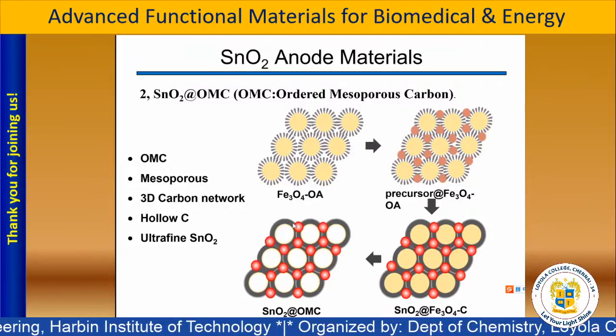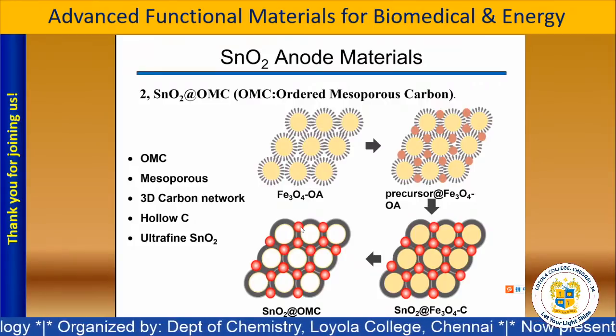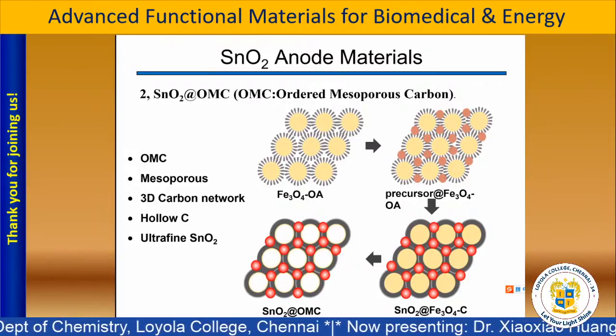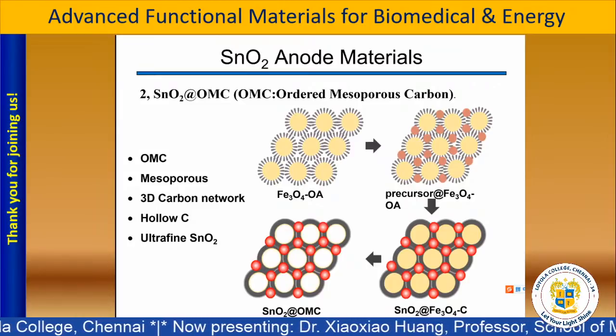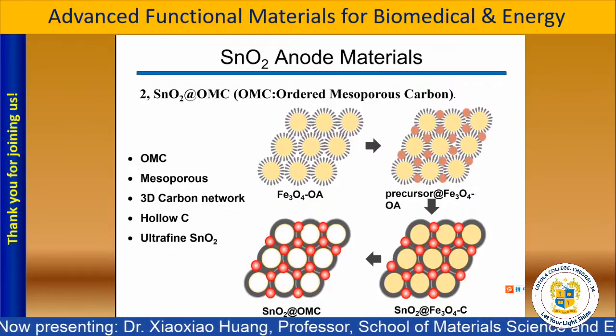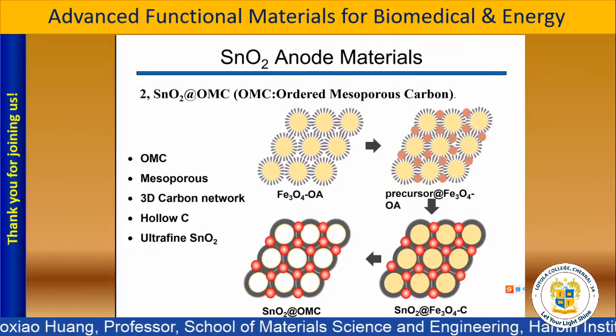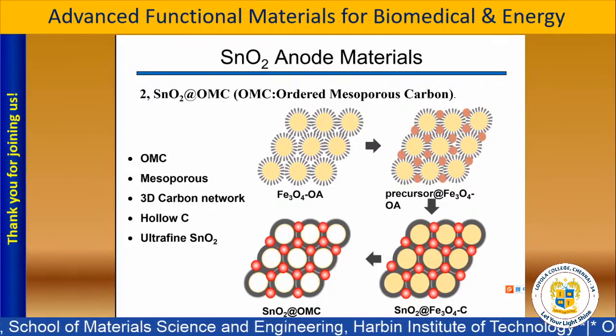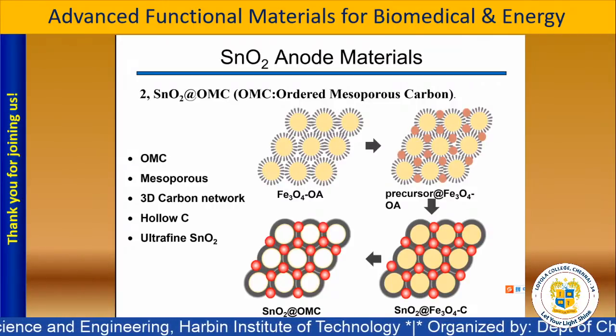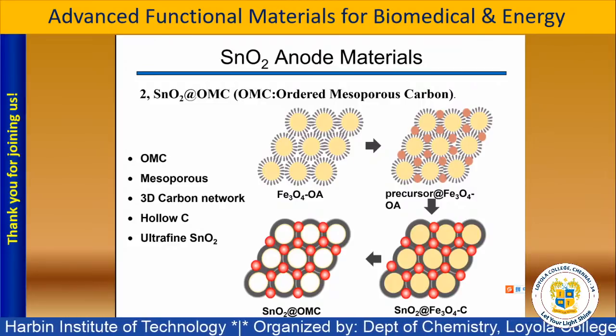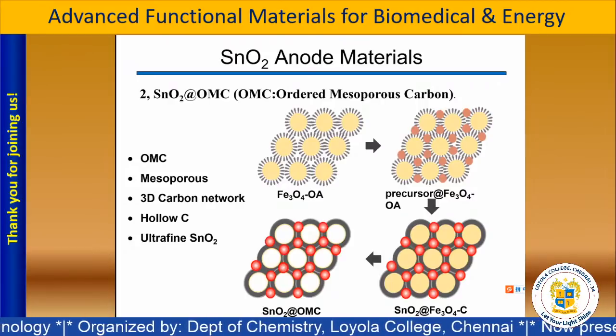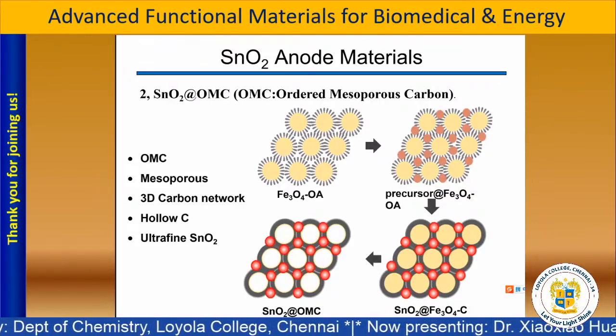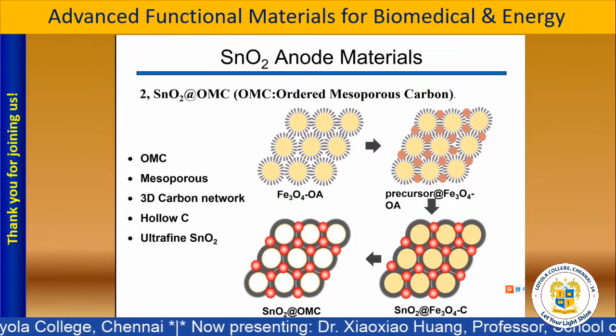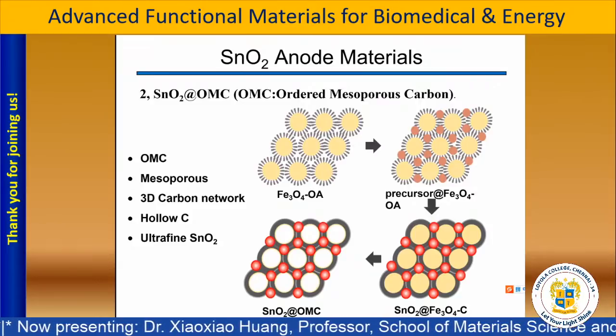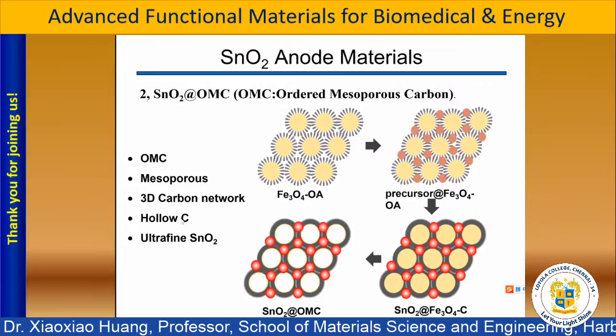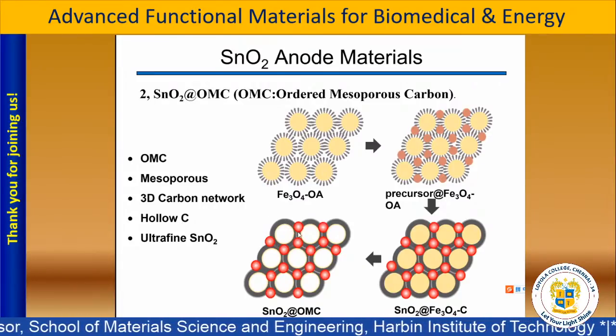So for this structure, when the tin oxide experiences bulk expansion, this hollow carbon structure will give a buffer or control role to help the tin oxide. That means that the tin oxide cannot be broken. You know, the tin oxide will have a very big bulk expansion. When the anode material experiences the charge or discharge process, the expansion should be about 358%. So it's a very big bulk expansion. But this hollow carbon will help it to control the bulk expansion.